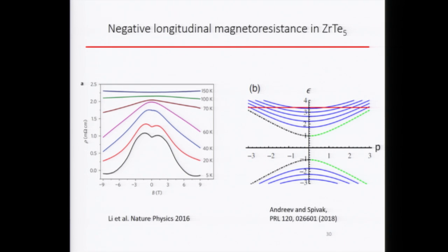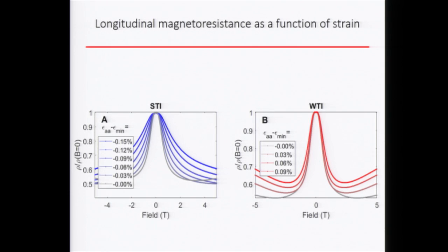This is kind of expected, since when your Fermi energy is away from a gap, it shouldn't be sensitive to what happens down there. Of course, when the gap increases, eventually this effect will disappear, and the degree of weakening should depend on the ratio between mass and Fermi energy as well. So we have also done the same longitudinal negative magnetoresistance measurement. We observe the longitudinal negative magnetoresistance, and what is even better is that we actually see very strong modulations of it.